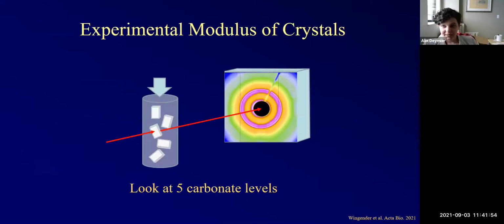So what we did is that we went to the DESY synchrotron particle accelerator that produces essentially lasers, so monochromatic beams of X-ray. We went to Hamburg to do this. And what they have is a pressure chamber, which is X-ray transparent. So we took crystals with 5 different types of carbonate, so B-type, but different levels. And we pressurized them by putting them in PBS and essentially cranking down the pressure. Like we had to manually crank down the pressure. So we're applying a stress through hydrostatic pressure.